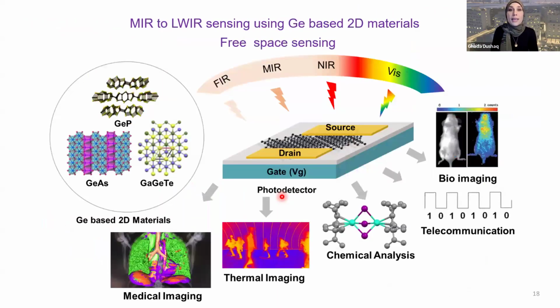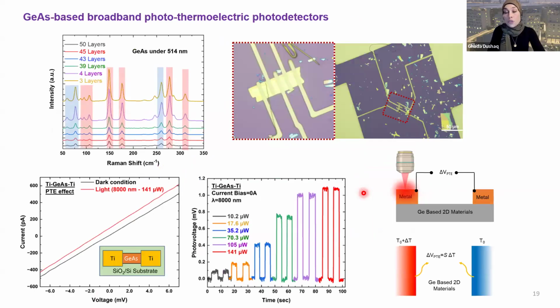The last thing that I want to say is the capability of this material to be a broadband detector. And this is also a very vital application, because we always lack a very high detectivity and high sensitivity material in the mid-infrared range, which this material can be of great interest for, for broadband cameras, thermal imaging, medical imaging, also surveillance. So we had some preliminary results on germanium arsenide because of the high Seebeck coefficient. So it's an uncooled mid-infrared detector that can work at 8 microns. So this is just ongoing research on mid-infrared.